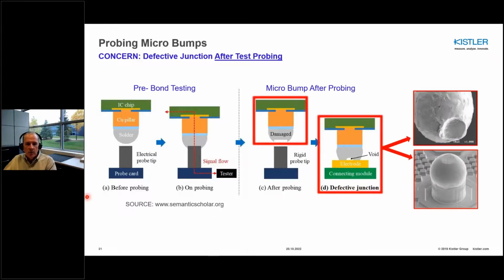However, we can see on the right portion of the slide, after this electrical test, the bump pad surface is mechanically damaged, a divot results. If this is not caught right away, this chip or batch of chips are later discovered defective during in-service operation. In test probing, it is desired that the micro bumps are not hit with too much force, as this can lead to both mechanical and electrical reliability issues.